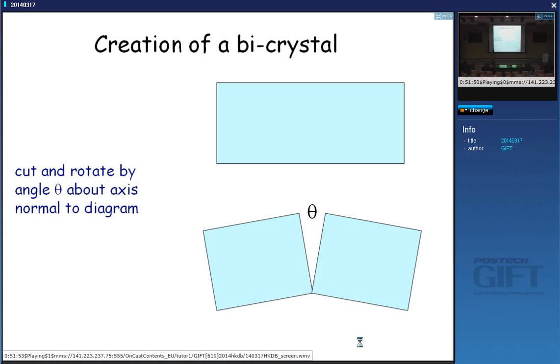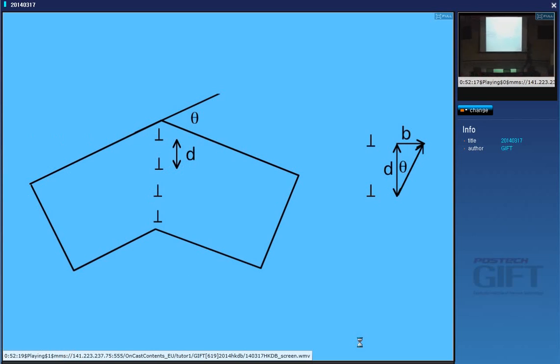And we don't see such holes when we look at a grain boundary. When we look at the structure, it's completely filling space. So there's something missing here. What I need to do is put material in there, so that it fills that triangular hole, right? And that material is dislocations. So an edge dislocation is basically like an extra plane, right? So that's like filling in the hole with extra planes. So here is an array of dislocations.